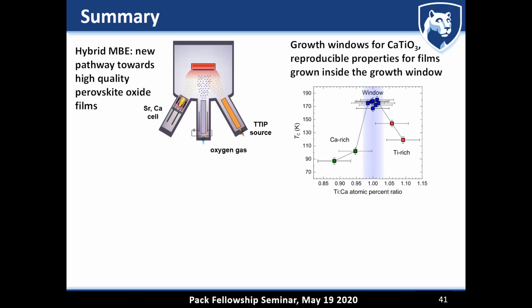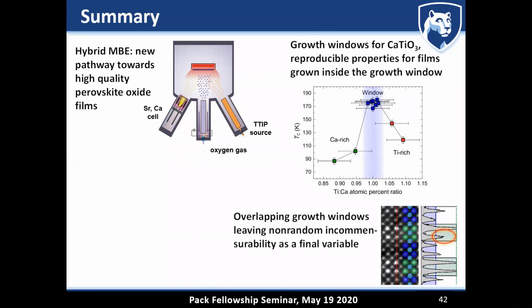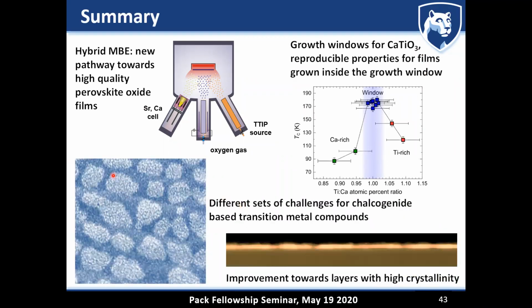And then we have shown that we can generate this growth window, and then ultimately that we are being challenged with a different set of roadblocks for the growth of chalcogenides. What you see here is an AFM image of a submonolayer coverage of platinum diselenide on sapphire. You can see this island formation, which ultimately, if you keep growing and annealing it properly, you can bring into a two monolayer platinum diselenide that's covering the entire substrate. And so with this, I'm going to stop, and I'm going to be happy to answer questions.